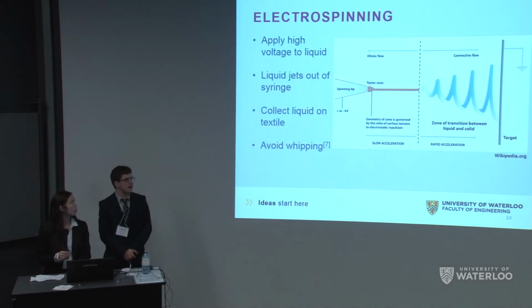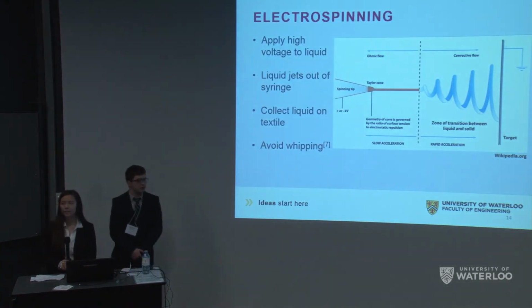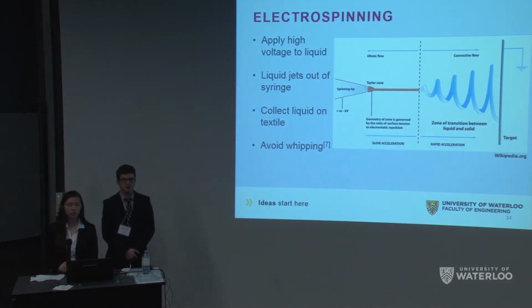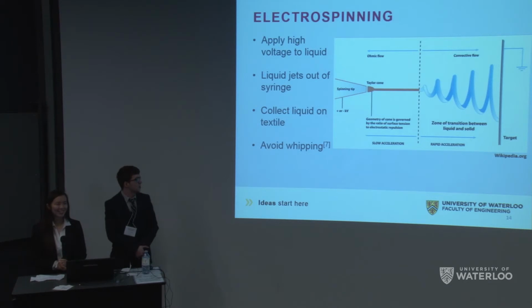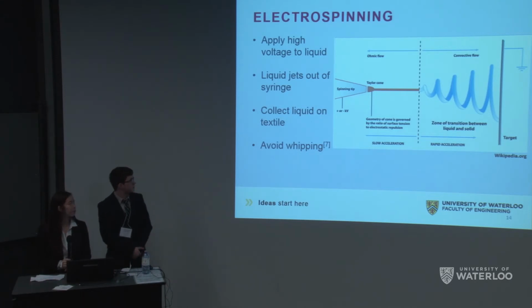So let's take a look at exactly how electrospinning works. So the liquid that you use is the material you want to deposit on your substrate, and it's mixed in with a solvent. So when you apply a high potential to the liquid, through electrostatic repulsion, it causes it to jet out of your syringe tip, which you can see in the orange. As it travels through the air, charge migration to the surface causes it to eventually eject in a whipping-like fashion, which you can see in the blue. Finally, it reaches your substrate and is deposited. This whipping fashion is not desirable due to the fact that your nanowires will have some characteristics of this and weaken the alignment that you get.